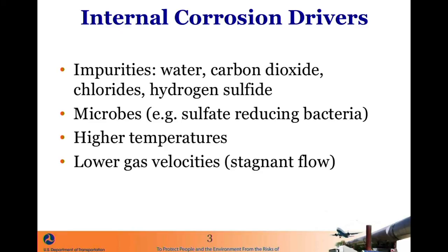So here's a list of some of the impurities. We try to keep out water, carbon dioxide, chlorides, like what may be found in salt, and hydrogen sulfide. Some of you may have heard the term sour gas. So hydrogen sulfide results from organic decomposition, like the rotten egg smell, and we try to keep that out. Other things that may occur is if water is present inside the pipeline, bacteria, microbes may grow, and essentially they poop acid, which will dissolve the steel. So that can occur on liquid lines.